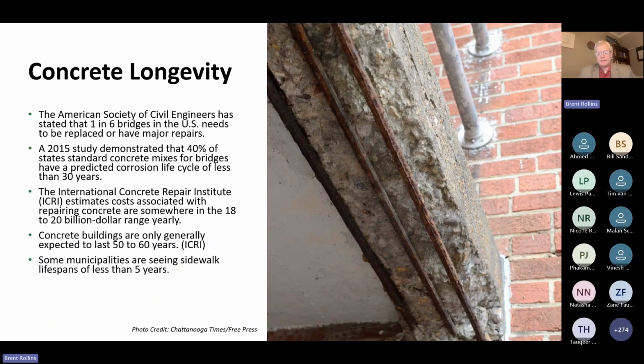Now, we have something in the U.S. that you don't get too much exposure to in South Africa, and that's freeze-thaw and de-icing chemicals, especially in the northern states. I will say that most of the municipalities that I talk to that are having short lives on sidewalks, it is due to de-icing chemical attack, whereas with the beautiful coastline you have in South Africa, much of your salt attack is going to be coastal salts. But we're not just talking about salt attack here. We're talking about permeability and all of the things that can affect concrete. It just so happens that reinforcing steel corrosion is the number one reason. So we're going to spend quite a bit of time on reinforcing steel corrosion.